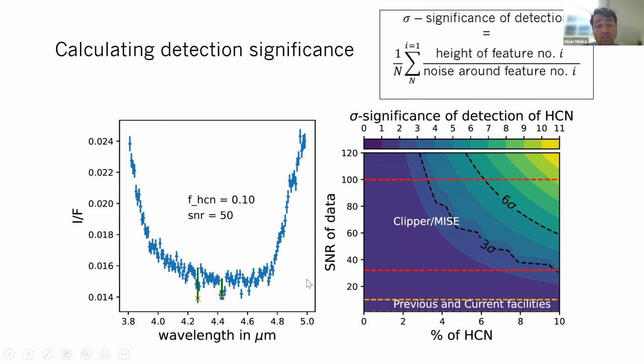What I'm interested in is how strong these features are, so how much they stand out with respect to the background noise. That is what I'm defining as the sigma significance of the feature, basically how far out it is from the average noise. When you do that for different amounts of hydrogen cyanide and different SNR of data, you see that, as expected, for a larger amount of the trace species and larger SNR data, the significance of the feature increases, especially within the SNR limits of Clipper.